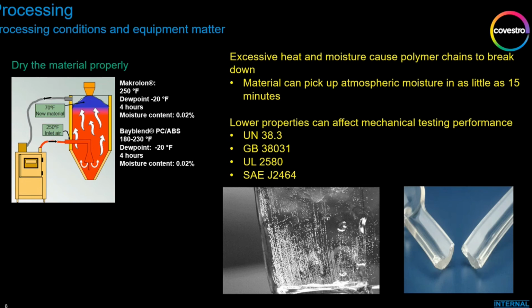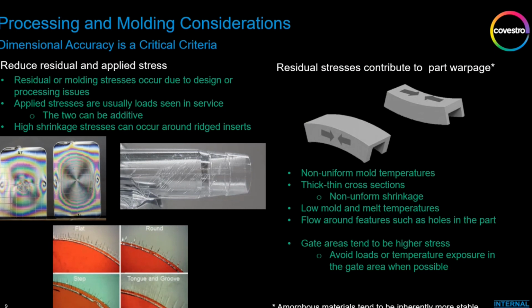And so you want to make sure that your equipment is drying the material properly to that 0.02% level. If you don't get to that level, that's when you can start to have issues. Excessive heat and moisture can cause the polymer chains to break down. That's going to affect your material properties, and then it can also give you cosmetic issues. Again, you can see we have streaks, we have issues in the part itself. Cosmetically, that looks bad, but it can also affect performance, again, if we're trying to UV cure through that material or we have other optical requirements.